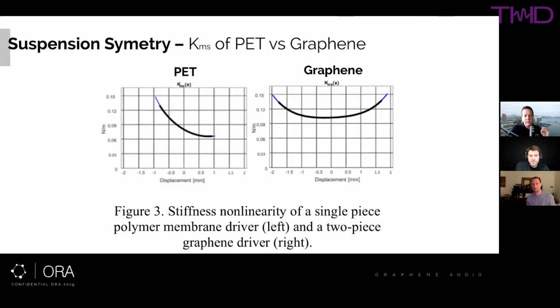So you eliminate glue, so it eliminates a little bit of mass. When you're talking about 40 millimeter down to 6 millimeter drivers, that little bit of mass and the consistency helps out a lot. That's very interesting. Sometimes we struggle to find the right suspension for this material. There's a lot of interaction between the cone and the suspension. That's very interesting, actually. Check that out. Those guys I'm speaking of are early stage as well, so you guys might be able to help each other.